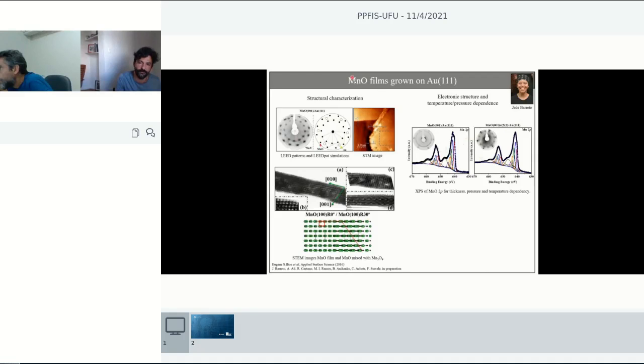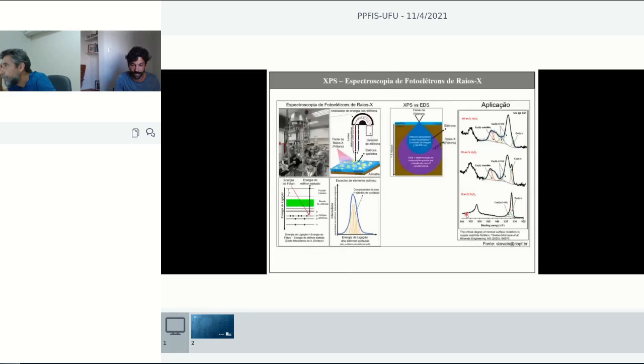And this is very useful because for now we have a very nice model for the MnO film. At the same time, we can also, with the spectroscopy signature, judge how much we have of low coordinated sites of manganese in this oxide. So it is a nice way to not only prepare a nice system to be investigated in future adsorption reactivity studies, but we also add to the interpretation of these lines here.